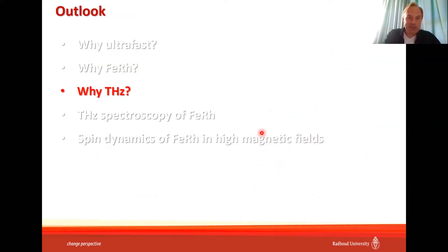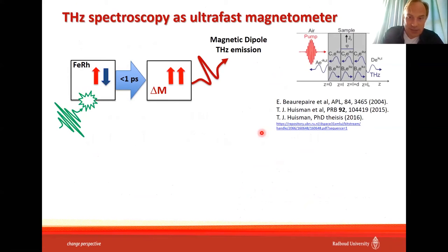We started to think about possibilities to use terahertz for the studies of ultrafast dynamics. How can we do this? There are two reasons why terahertz may help us to see ultrafast emergence of magnetization. The first mechanism is based on magnetic dipole emission of terahertz radiation. So if you have an antiferromagnet, you pump it with a short laser pulse. Imagine that the antiferromagnet goes to a ferromagnetic state on a time scale of 1 picosecond. So it means that within 1 picosecond, suddenly there is a magnetization in the medium. And this magnetization, according to the wave equation, will emit radiation. And if magnetization appeared on a time scale of 1 picosecond, the radiation would be in the terahertz spectral range.